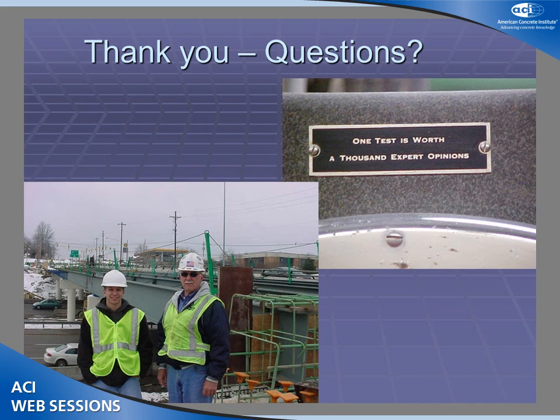Question back there? Yeah, you talk about thin overlay. How thin are you talking? Standard bridge deck and even some pavement overlays on CRC in Texas, those can be 2-3 inches. Sometimes they use latex modified overlays, which are fairly expensive, but I think the record has shown that plain concrete can work pretty well, but you really have the issue of possibly losing bond. And so I think you have the issue of differential shrinkage between the overlay and the base, and you have the issue of promoting bond at the interface.